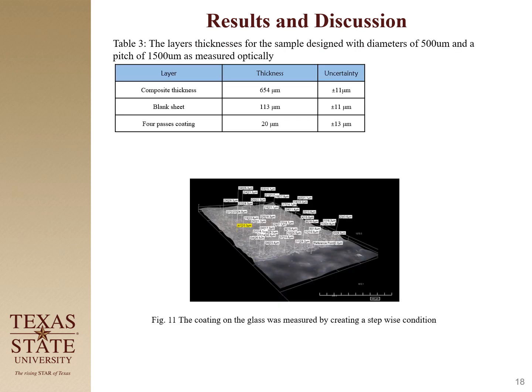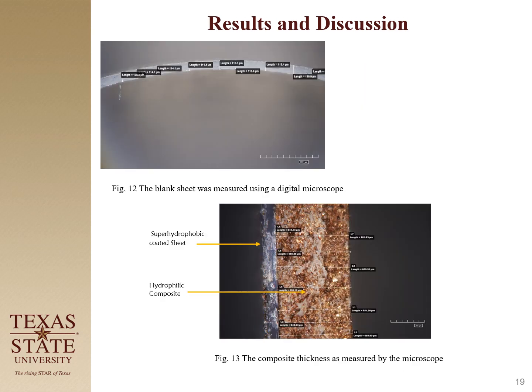Now, for the thickness of the layers, I use an optical microscope, a digital microscope, and for the 4-layer coatings, I put a tape and coat it, then remove the tape to create a step, and thus measure the thickness. Here you can see the thickness of the sheet without any coating, and finally the measurement of the composite part of the sample.